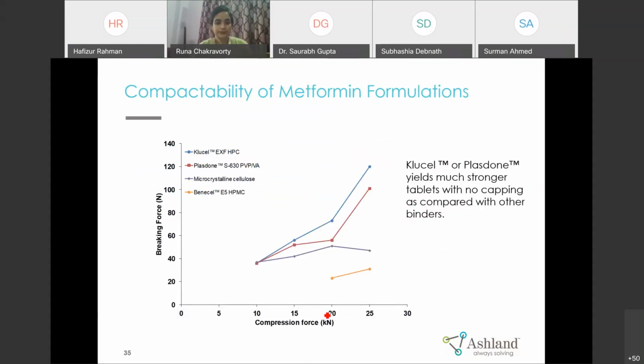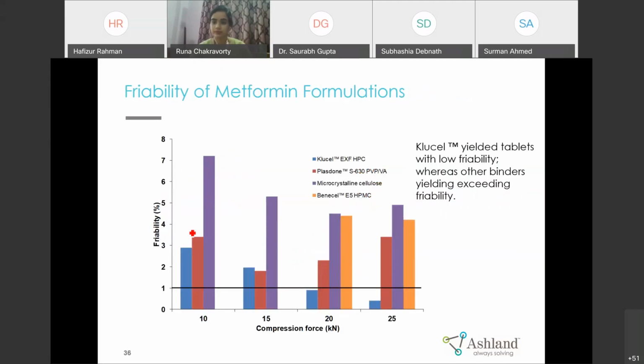So again, we compressed tablets at different compression force and checked the tablet hardness, and we found that tablets containing Klucel EXF give us the stronger tablet, and next to Klucel EXF, we got the stronger tablet with copovidone. As we have seen that tablets containing Klucel give us the stronger tablet, that is also reflecting in terms of friability. We get the lesser friability with Klucel EXF followed by copovidone. So you can see that at a higher compression force, friability with Klucel was much lesser when we compared with other binders.